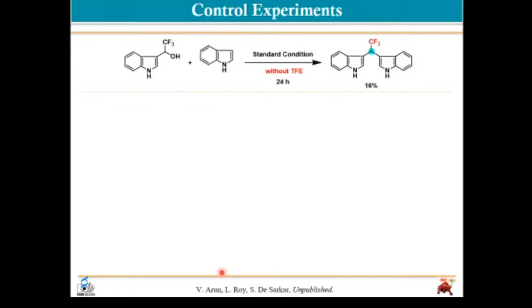So what we did, we synthesized, initially we were taking what? Indoles only. Now we intentionally synthesize this molecule with CF3OH using some other methods. Then we mixed these two under our standard reaction conditions, and we got 16% yield of the product. Although the yield is low, it's a control experiment, so we don't care much. Now, as you can see, if we use this indole and there is no other trifluoroethanol source, the CF3 must be coming from this. So this control experiment proves that this molecule is an intermediate of our reaction. In the mechanism, at some stage this is forming, and then it's reacting with another molecule of indole and forming this bis-indole product.